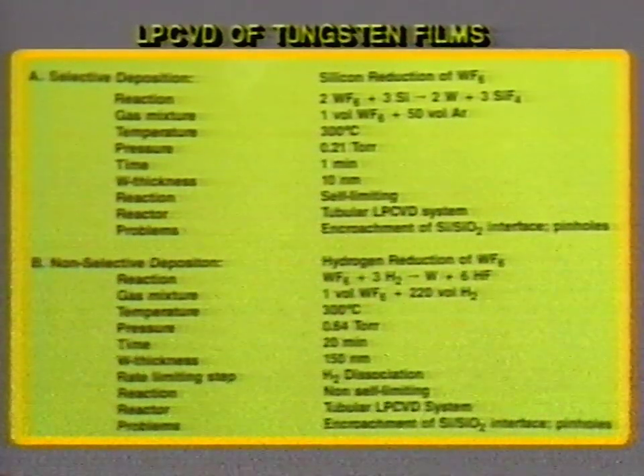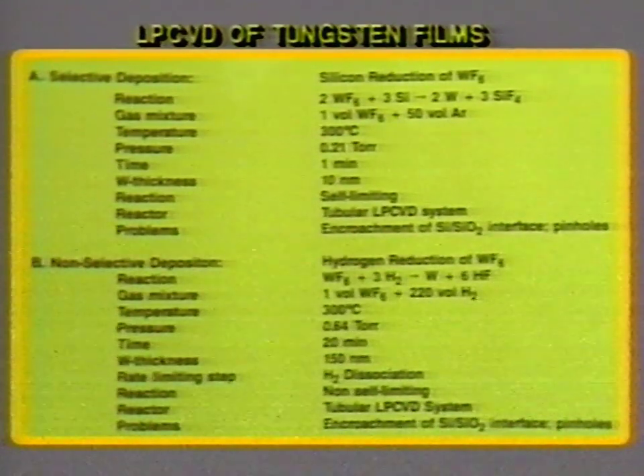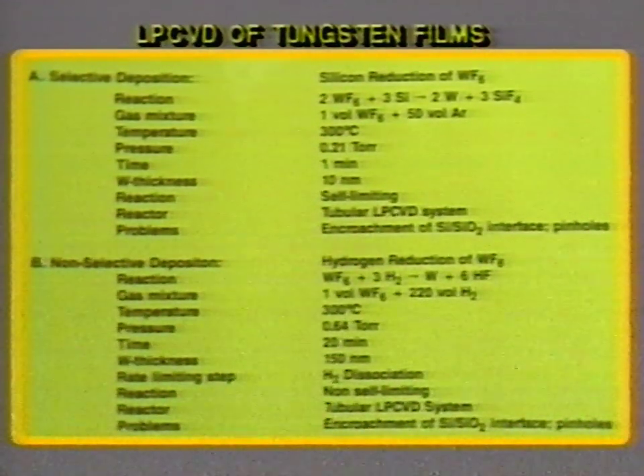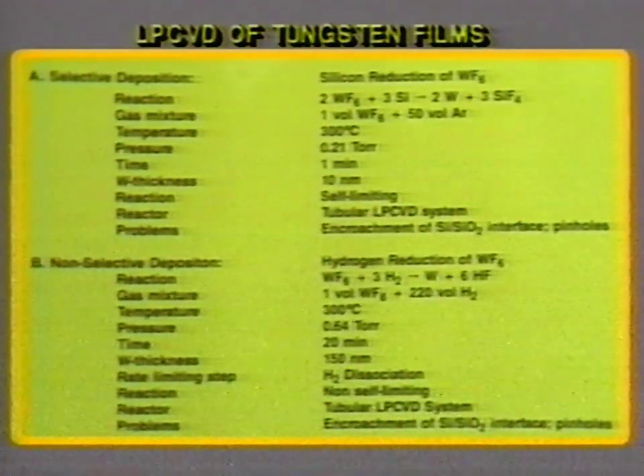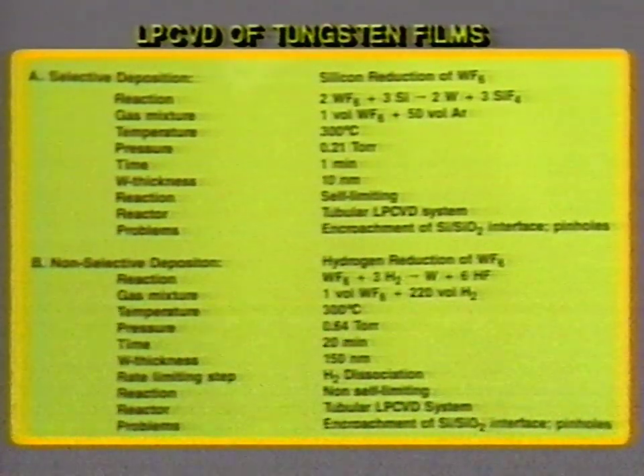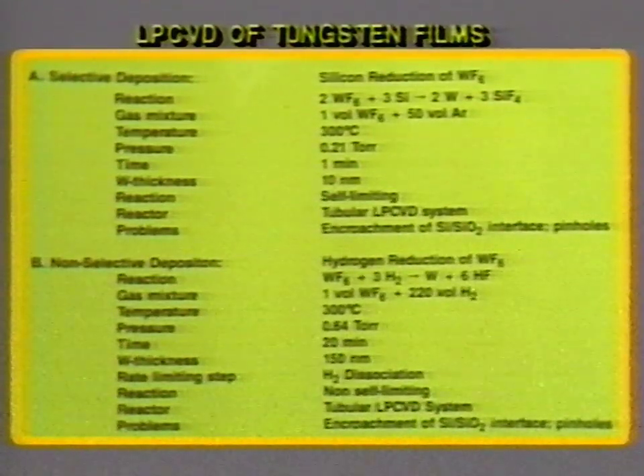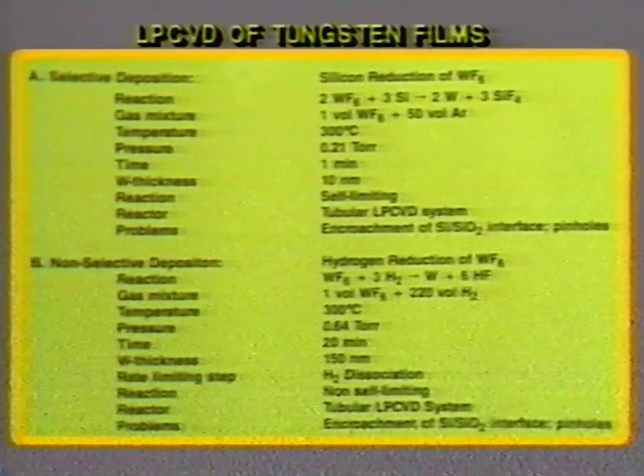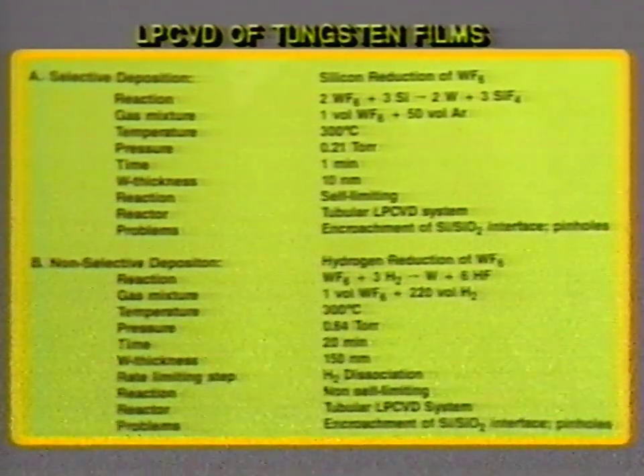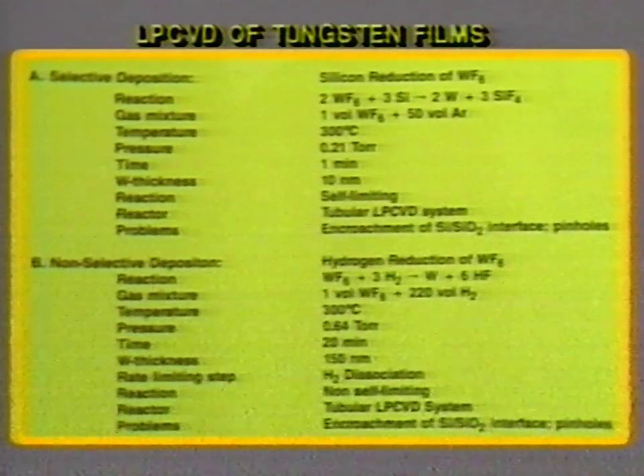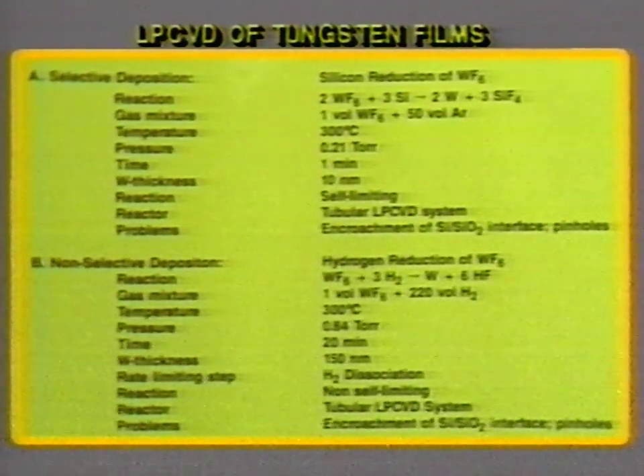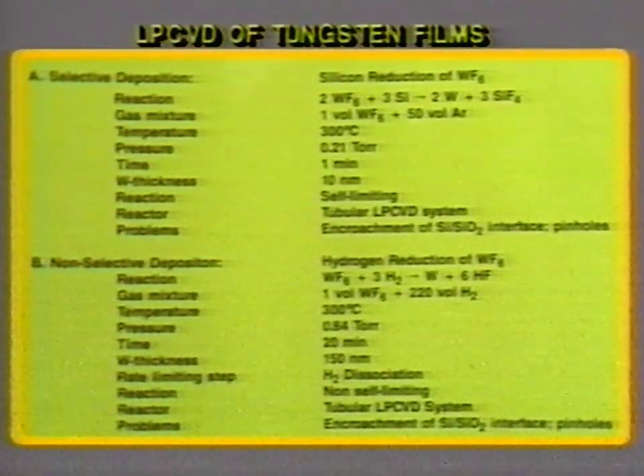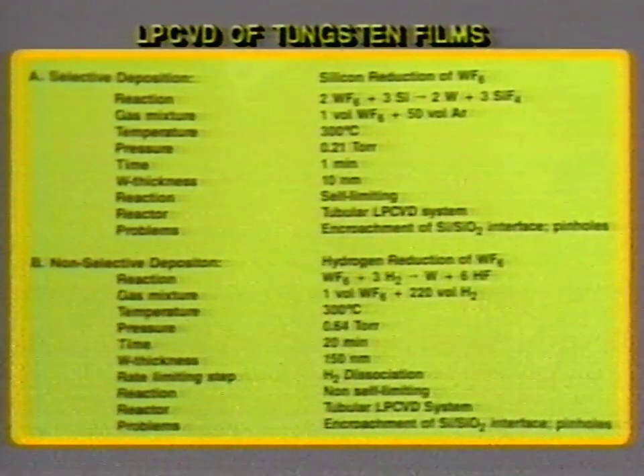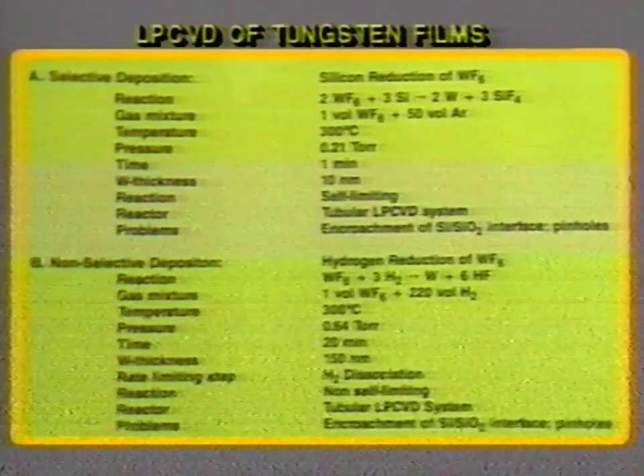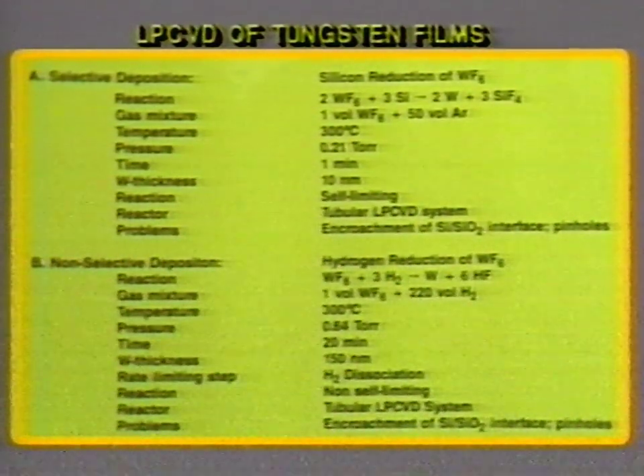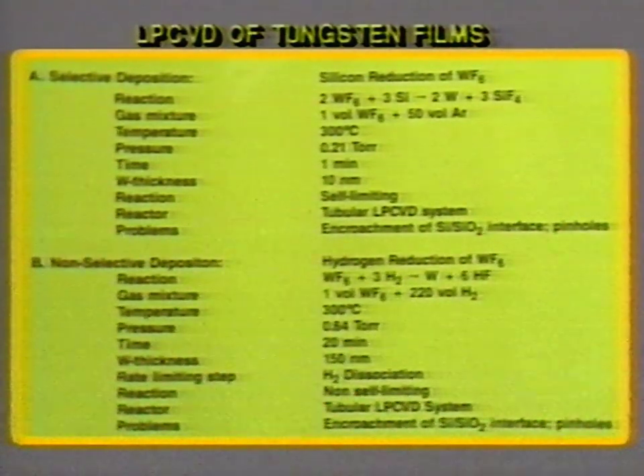However, you can continue the reaction by now introducing hydrogen to the mixture. And the hydrogen, of course, now acts as the classical example of metal reduction from the fluoride to produce tungsten by formation of HF vapor. However, the reaction can still be continued for some time as a selective reaction. Namely, a preferred reaction is still taking place on the tungsten which we formed here. In other words, we can build up this thickness to an additional level using this process, because the deposition is preferably taking place on the tungsten itself.